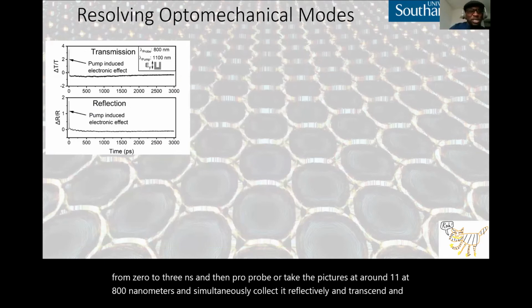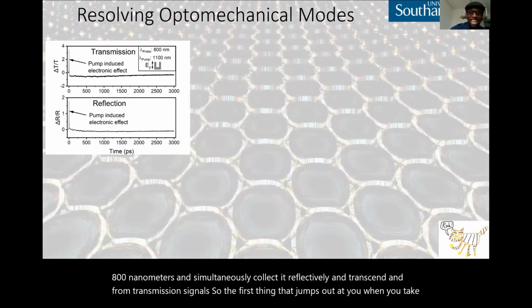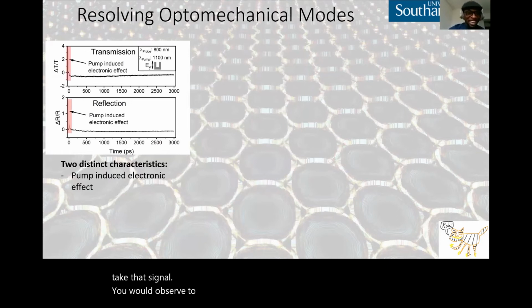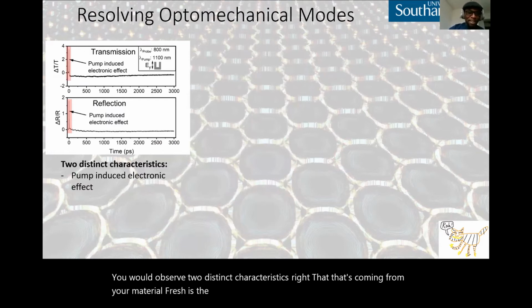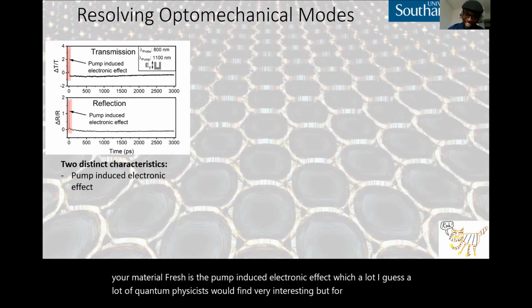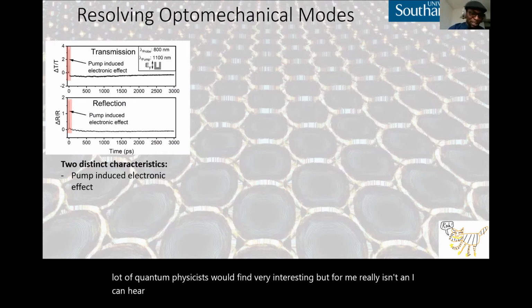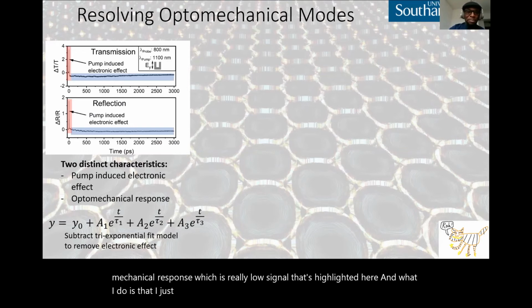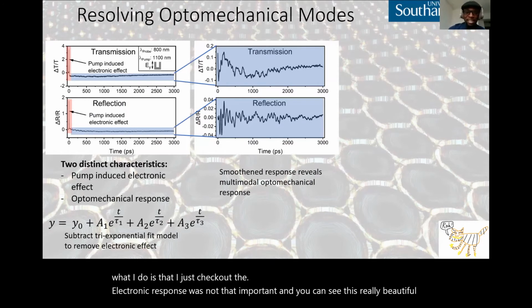So the first thing that jumps out at you when you take that signal is that you'd observe two distinct characteristics, right? That's coming from your material. First is the pump-induced electronic effect, which I guess a lot of quantum physicists would find very interesting, but for me, it really isn't. And I can hear their collective gasps. The second one is the optomechanical response, which is this really low signal that's highlighted here. And what I do is that I just chuck out the electronic response because it's not that important. And then you can see this really beautiful optomechanical response of my signal.